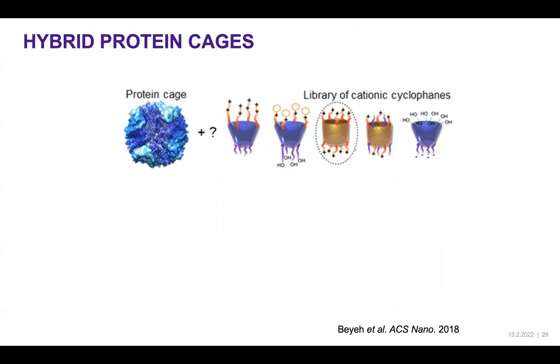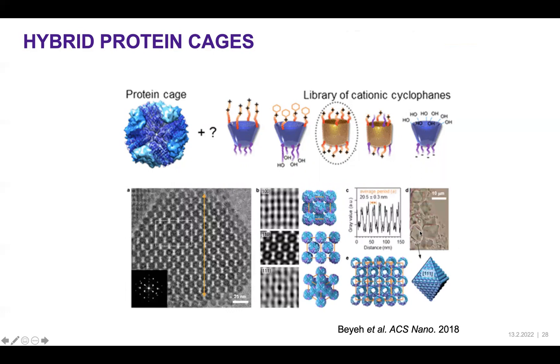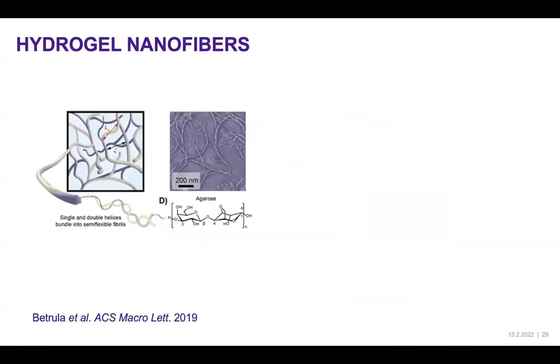It's not only for biological particles — we can make hybrid particles by reacting synthetic molecules with protein cages, which leads to large crystals. Since these crystals are not stable, the only way to identify how the protein cages are arranged when interacting with the synthetic molecule is using cryogenic electron microscopy, where we can get the diffraction pattern, identify the inter-particle distance, and determine the unit cell and lattice constant. It is a very good complementary technique to support solution observations such as small angle X-ray scattering.